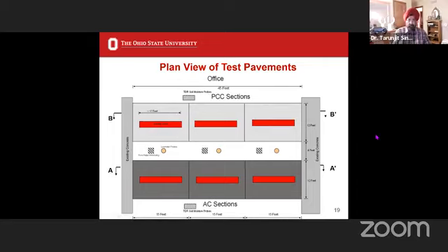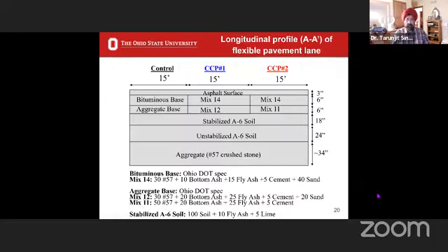So you're coming back to the concrete and the asphalt. This is where the tire will run over this. As a result, it is only the central area that has sensing. And this gives you an example of the flexible pavement. The control section has no CCBs in the base or the aggregate. And then we had base and sub-base, different mixes that had different amounts of fly ash added to them. Below this, we had 18 inches of stabilized A6 soil, and then we had unstabilized aggregate. And then the tire would go over the top of this, each of these in this direction.